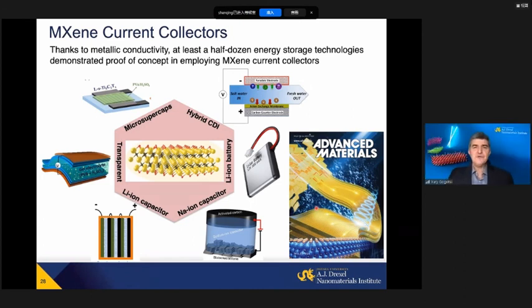Well, basically, you are right about many of these things, but there are a couple of things here. One, for example, in electrocatalysis, it has been shown in HER that unlike dichalcogenides, the entire surface is electrochemically active. However, the edge is a challenge. This is actually where oxidation in water or in air starts. So we worked to develop a process that keeps edges straight, which keeps the material stoichiometric. There are fewer points where degradation starts. So control is very important here.